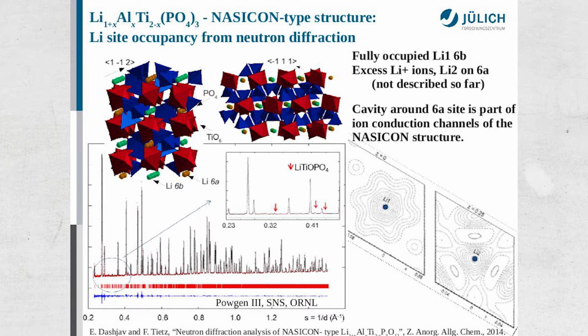And they wanted first to get a room temperature structure, a correct structure where you see the lithium. And that's where neutrons are good. They're good at seeing light elements like hydrogen and lithium. And here we use the spallation neutron source in Oak Ridge, where we operate part of the beamline. And you have this extremely resolved time-of-flight neutron diffraction spectrum. You cannot do this with X-rays because it would correspond to going to 720 degrees in two theta, which you cannot do. Okay? Or you would go to high energy and then you don't have resolution.